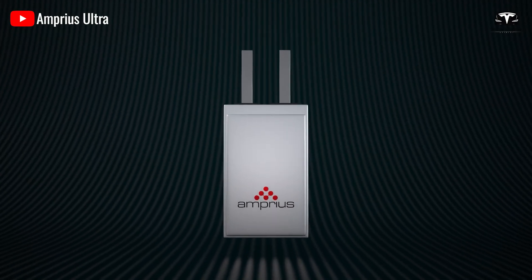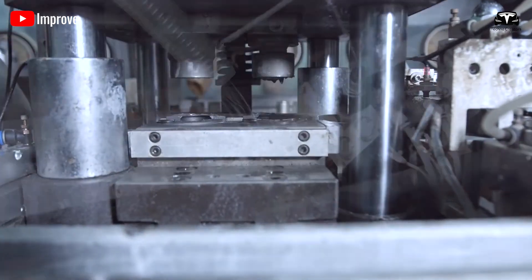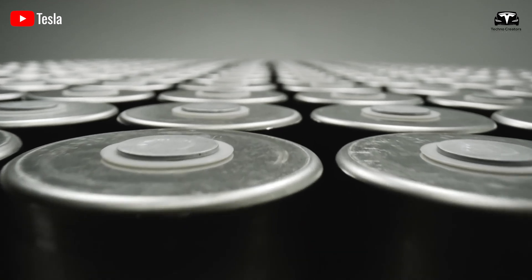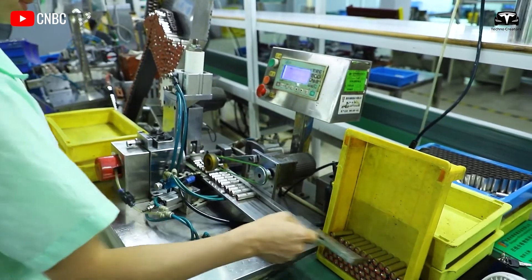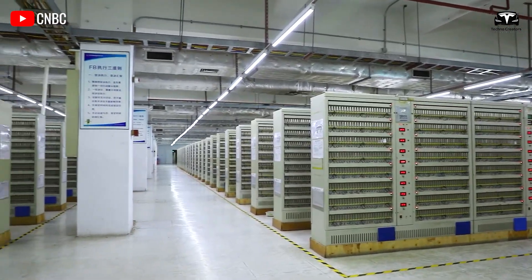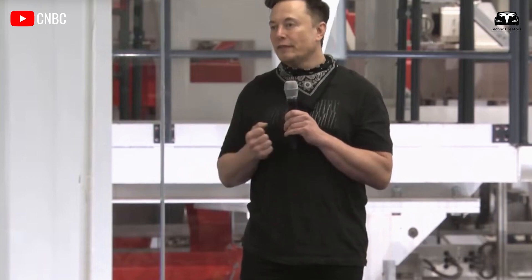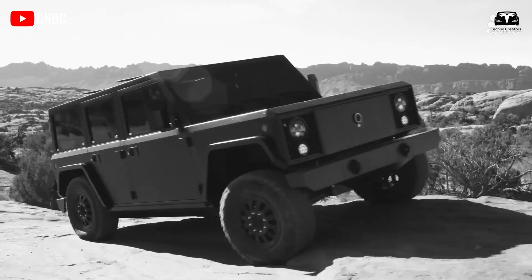What is the superior heat resistance of silicon anode batteries? Amprius's next-generation battery technology has been tested through impact and penetration tests according to military performance specifications to assess feasibility in combat situations. It passed the test without any smoke or fire effects. When measured with an infrared thermometer, the temperature of the battery cell only increased by 0 to 10 degrees Celsius around the area where the sharp object penetrated, demonstrating the puncture and fire resistance of the battery when applied to electric vehicles.